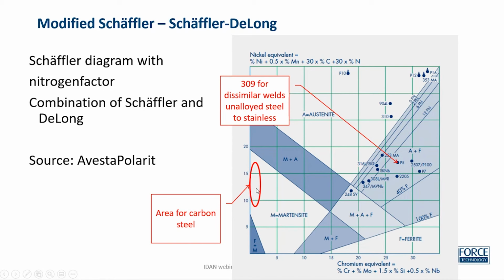then obviously if we just melt the two, the combined composition would be somewhere between these two, in an area with martensite or perhaps martensite with a little austenite and a high risk of getting cracks. So we don't want to be in that area. We want the weld metal to be here like the stainless steel itself. So we need to choose a filler material which could drag us into this area. And we can do that by using a filler like the Avesta P5, which is a 309 type of filler material. By that, we can get the combined weld metal into the preferred area in here.